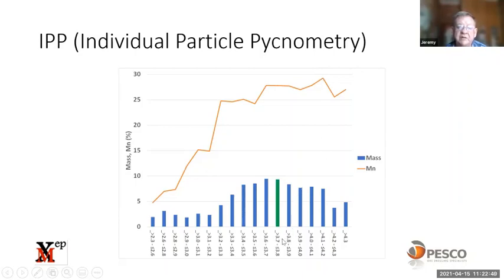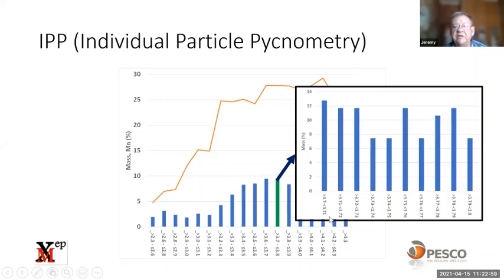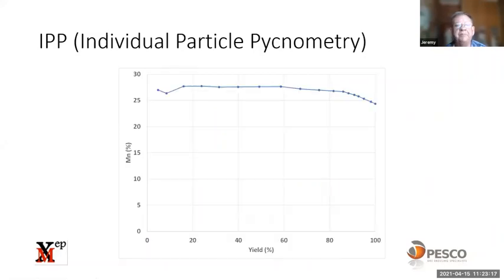But what's interesting though, if we target in now on the 3.7 to 3.8 density bin, because we analyzed each particle individually, we can then get more detail on that. So we can break down that bin into 0.01 density fractions, and that's the density distribution within that bin. So the individual particle pycnometry, because you're analyzing by particle, in terms of density, it gives you extremely high resolution. Here's the grade yield curve. You can see here, if you're targeting, say, a 30 or above, this sample wouldn't make it.